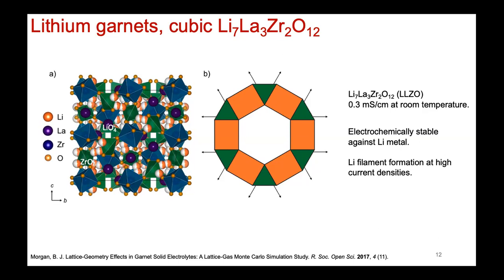But let's look at the ion conductivity as a function at room temperature. You can see that it's 0.3 millisiemens per centimeter. So it's still not as high as 1 molar LiPF6 in ethylene carbonate dimethyl carbonate 3 to 7 by volume, but it's getting up there, right? So this is what's called high ion conductivity, but it's not so high that we can readily replace liquid electrolyte with this compound alone.